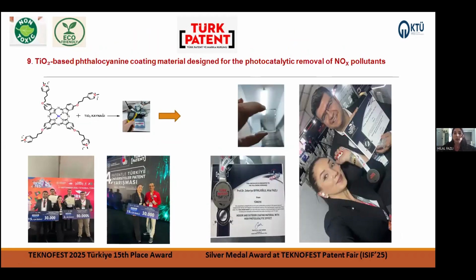This study was carried out at the Department of Material Engineering at Politecnica della Marca University in Ancona in Italy. We investigated the effect of the original titanium dioxide-based coating material containing peripheral tetra-substituted nickel phthalocyanine, which we synthesized, on the removal of nitrogen oxide compounds, known as a major air pollutant. As a result, it was determined that the titanium dioxide-based nickel-containing phthalocyanine coating material was 18 times more effective than pure titanium dioxide, which is commonly used for nitrogen oxide removal.